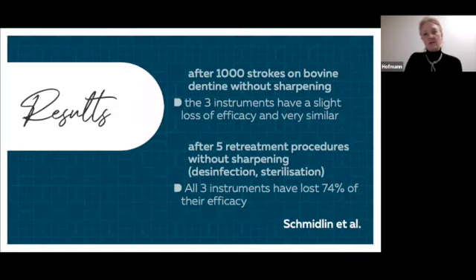And the results were quite interesting, because after 1,000 strokes on bovine dentin, the 3 instruments have a slight loss of efficacy, and very similar. There are little differences, but not statistically relevant. And after 5 retreatment procedures, so disinfection, thermodisinfector, sterilization, all 3 instruments have lost 74% of their efficacy. So actually at the end, all 3 instruments were blunt exactly the same.